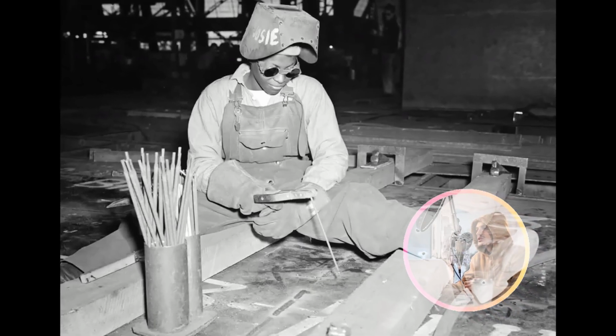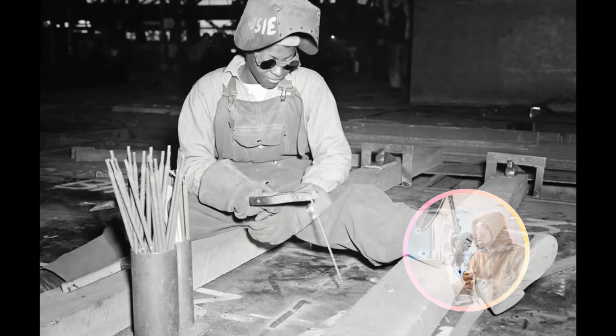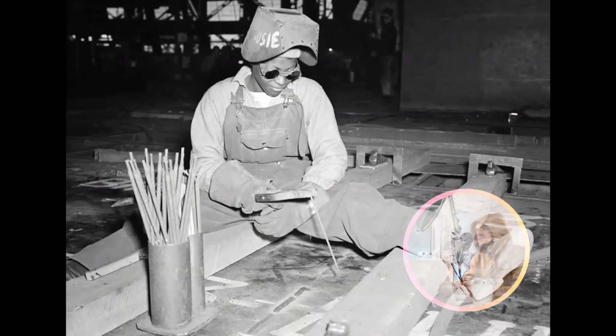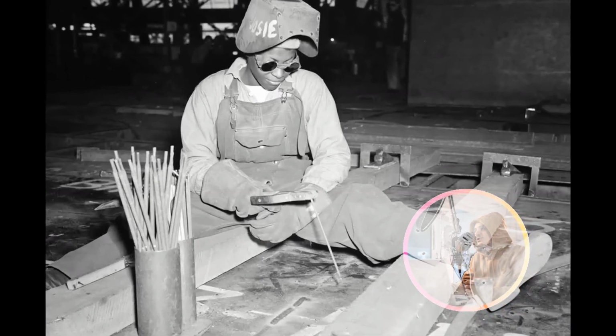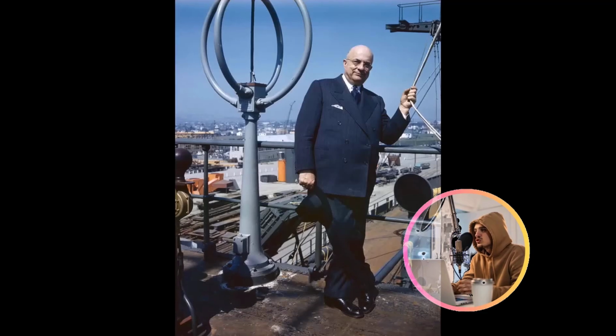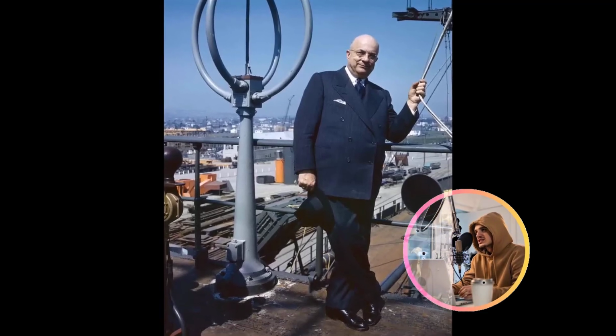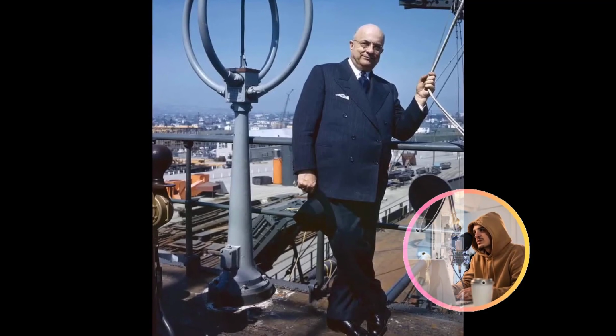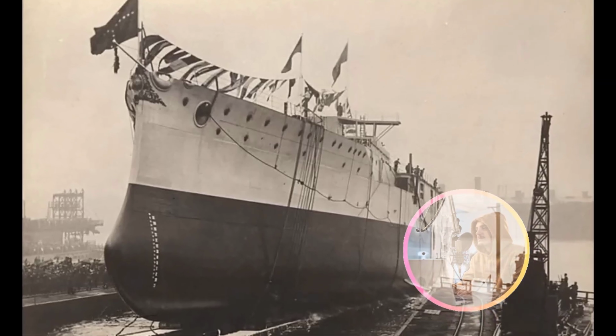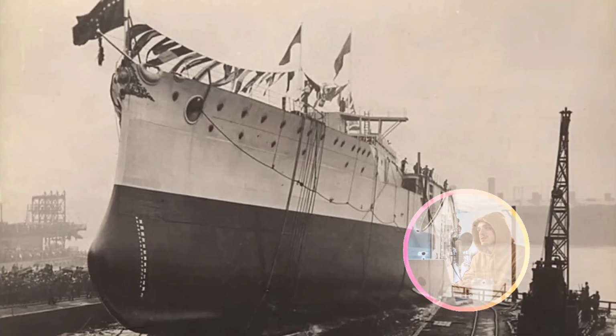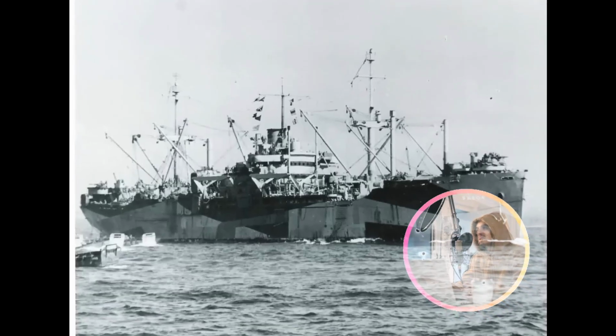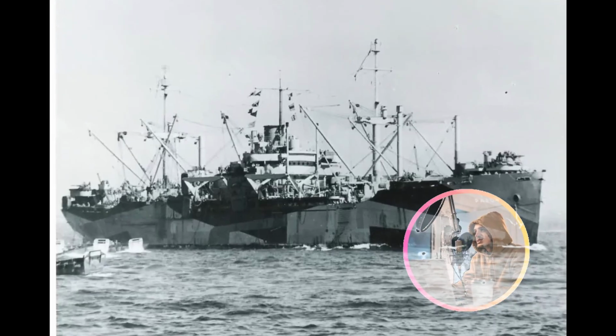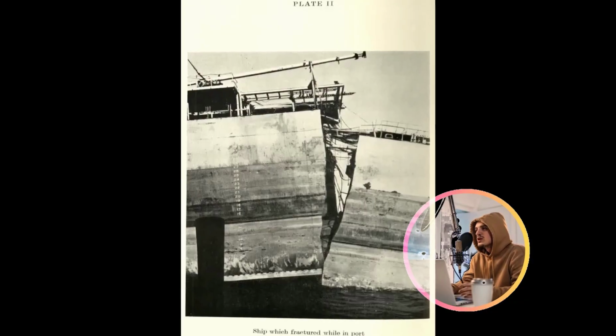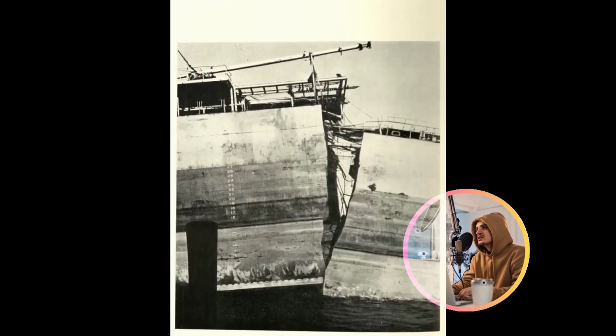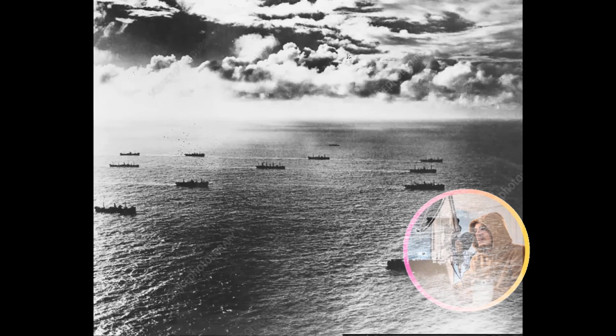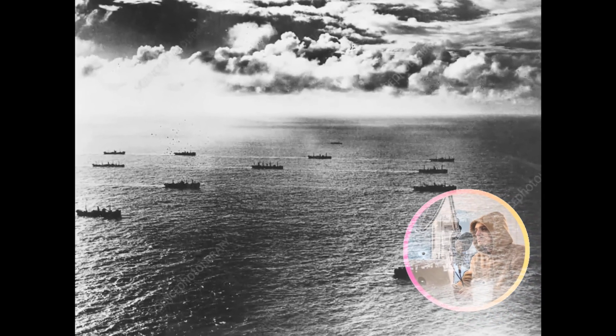The structural disintegration of the SS Schenectady, upon retrospective analysis, presented an entirely logical sequence of events. Her construction had commenced in the nascent months of winter, employing welding methodologies that inadvertently amplified the inherent residual stresses within her metallic framework. Consequently, the vessel's hull harbored an immense burden of tens of millions of pounds of internal, constrained tension. As the dawn broke over Portland, bringing with it a precipitous drop in temperature to a frigid 28 degrees Fahrenheit, the ship's steel abruptly lost its pliability, transitioning into a dangerously brittle state. The severe localized stress at one of her cargo hatch corners provided the critical point for a crack to originate.